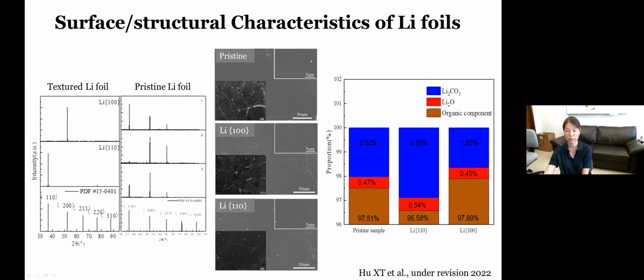And then in terms of the surface, we did clean the samples with THF solution of naphthalene. So that removed the surface oxide and resulted in a smooth surface. And they're very similar for all three different samples, right? We did have a bit more etching on the surface of the sample to see the grain boundary, so the size of the grains can be estimated as well. For the three samples, the pristine, lithium 100 and lithium 110, the grain sizes are in the range of hundreds of micrometers. So they're actually very similar as a starting sample, right? And again, we did XPS to look at the surface chemistry. For all these three samples, the surface chemistry is very similar as well. It contains a trace amount of lithium oxide and lithium carbonate, but the chemical composition is almost identical for the three starting samples.